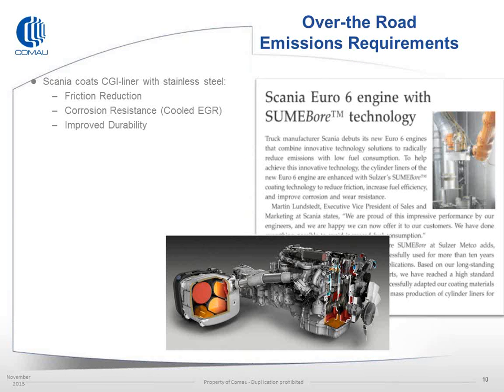As well, in the commercial market, what we're finding is companies pursuing technologies to allow them to increase their EGR. One of the problems with increased levels of EGR inside cast iron blocks is corrosion of the cast iron. By using a coating system and staying even with a cast iron block, you can replace the wear surface with a corrosion resistant surface, inhibiting corrosion, as well as being able to reduce your friction by the inherent porosity of the coating. And then of course now you have a harder coating in the surface. It increases the durability of the engine.